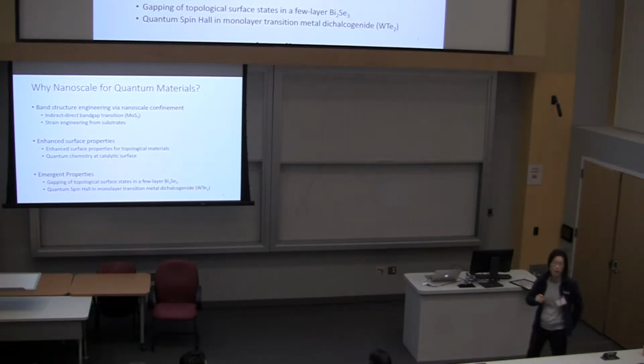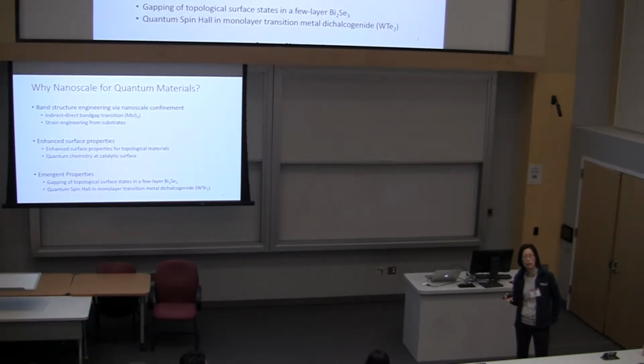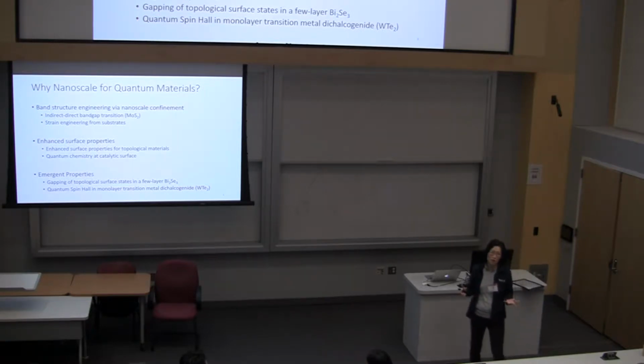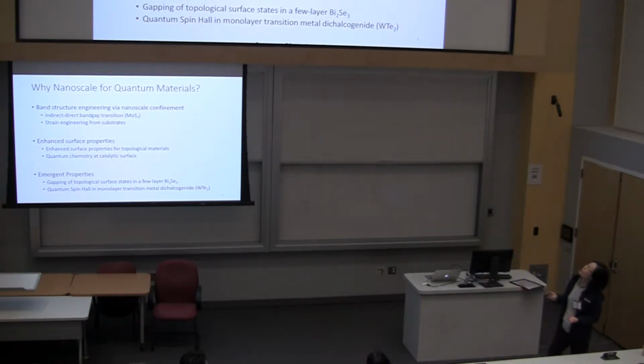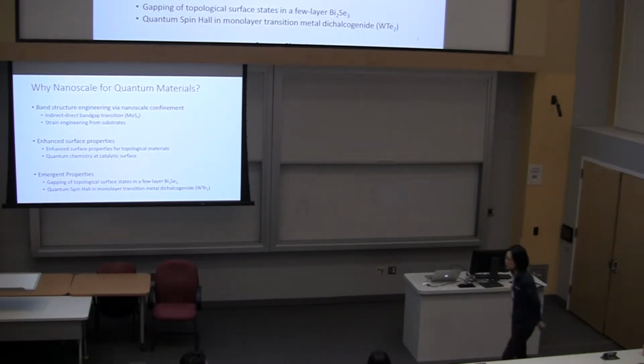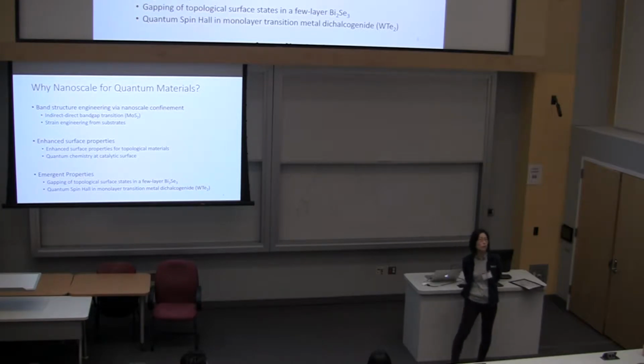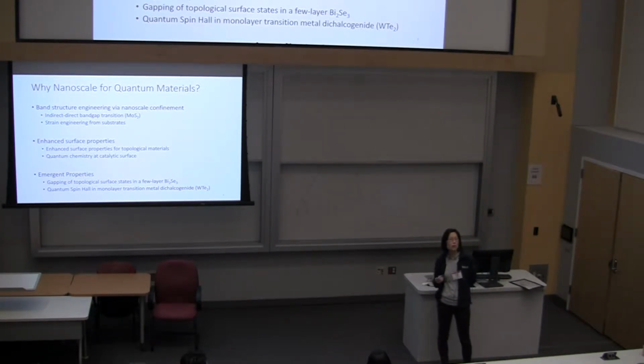At the nanoscale, especially for a single layer of materials, two-dimensional materials, you can do quite effective strain engineering from the substrate. Unlike in bulk, where it's very difficult to apply strain through the substrate, here that's pretty effective. And that can be another way to tune your band structures. Now, for topological materials where we care about the surface electron states, going to nanoscale is good because you're simply going to remove as much bulk as possible. So you're trying to enhance the surface effects that you're looking for.